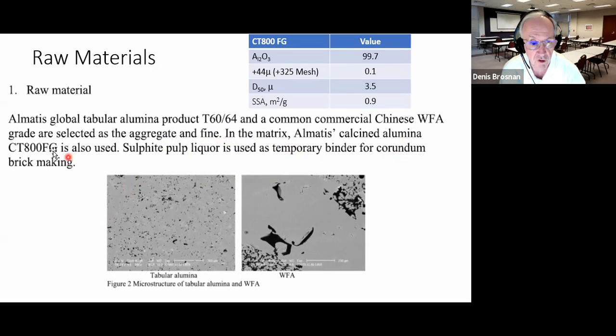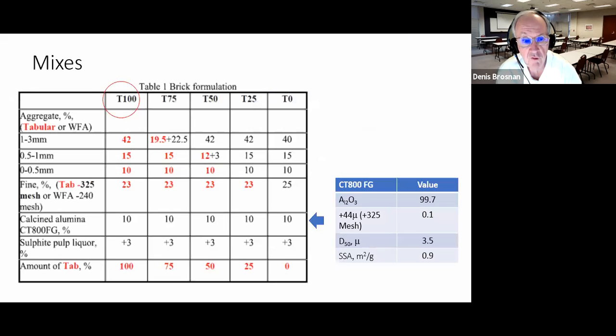These compositions contain CT800FG. Here's some information on CT800FG. You've seen it earlier, but we only have a very small percentage plus 325 mesh, 0.1%. The median particle size is 3.5 microns. The specific surface area is 0.9. When you look at this tabular alumina aggregate, back to the tab alumina, you can see little black pores here scattered among the microstructure. So we're going to look at some of their mixes.